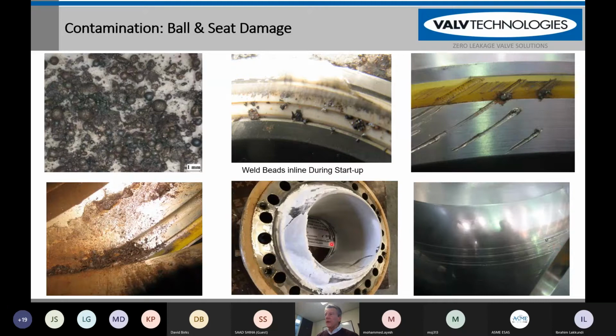As an example of that, let's take a look at when you're producing a pipeline and you're welding the pipe joints together. You get weld splatter that goes on the ID, on the inside of the pipe. Here is what weld splatter looks like right here. You can see it almost looks like little BBs, small little round particles of the weld slag that gets inside the pipes. And then when you start to flow or do your hydrostatic testing, this material goes down and gets embedded into the soft-seated valve, which, as you can see right here, weld beads in the valve during startup.